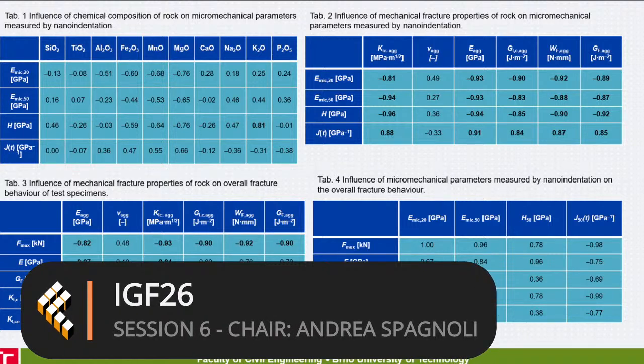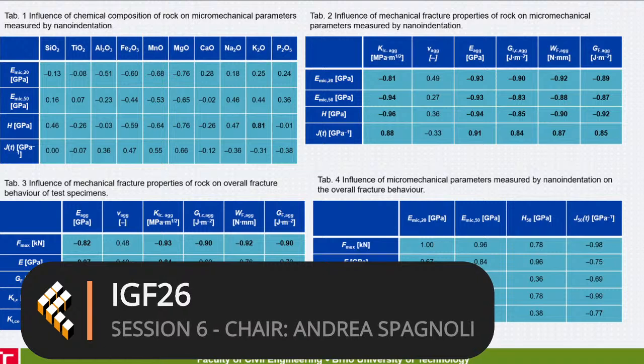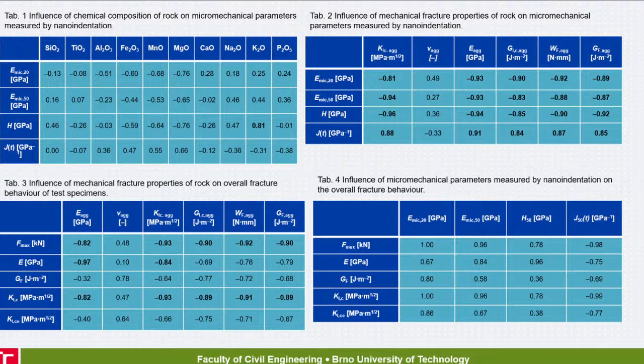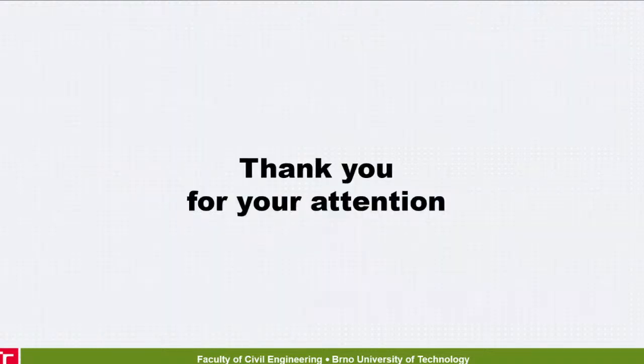The influence of mechanical fracture properties of rock on overall fracture behavior of the test specimens you can see in table 3. There is again almost no correlation or no strong correlation in the case of Poisson's ratio of rock material. And finally, you can see the influence of micromechanical parameters measured by nano-indentation on the overall fracture behavior of the specimens. It's in table 4. And we can see that there is a very strong or in some cases perfect correlation. So it means that the micromechanical parameters of the ITZ have a strong impact on the final fracture behavior. So that's all. Thank you for your attention.